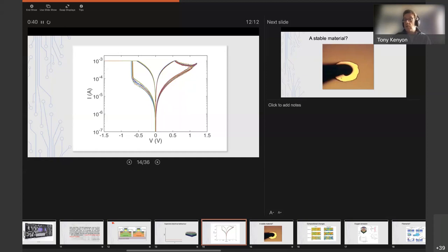So they go into the foundries, the fabs, and don't pose problems with contamination or diffusion during processing and so on. So there's actually quite a limited number of materials that we can consider. In terms of oxides, silicon oxide is the most fab friendly that you can think of, because it is the native oxide of silicon microelectronics. There are other oxides such as hafnium oxide, which is now widely used as that gate oxide for various reasons, rather than silicon oxide. And there are maybe a handful of others that might be useful or certainly fab friendly.